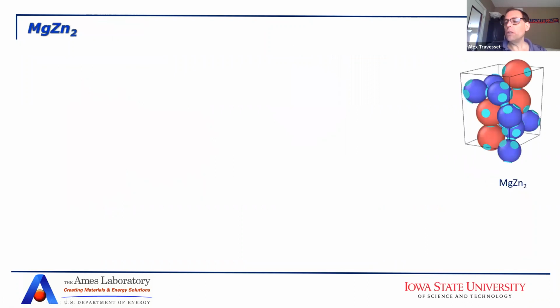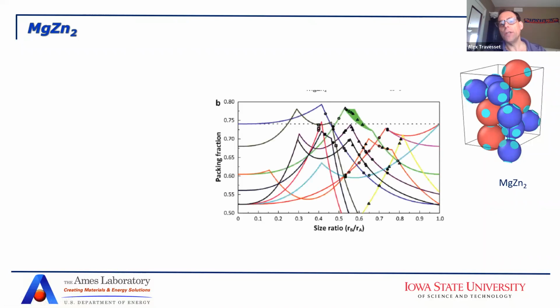So just to illustrate an example, this is actually the case for magnesium zinc 2. Magnesium zinc 2 consists of 2 interconnected lattices, one which consists of a diamond structure, the red ones, and another which is a pyrochlore lattice, which is the blue ones. The red ones have coordination 4, and then according to these OTM rules that I already introduced, those can be deformed and form vortices. The blue ones have coordination 6, and therefore they should behave like hard spheres.